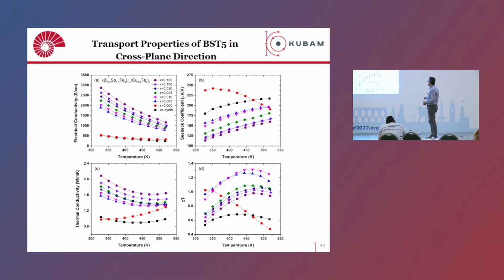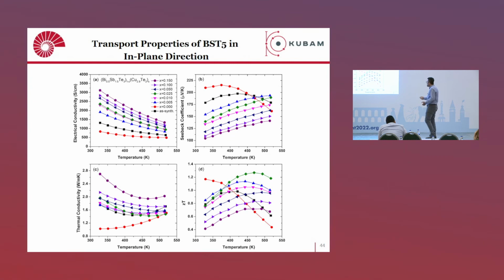So this was the cross-plane direction. We see a similar effect in the in-plane direction. The trends are almost the same: higher electrical conductivity, lower Seebeck, and a little bit higher thermal conductivity. The ZT is around 1.2 when 10-minute ball milling is applied, and at higher temperature, a copper telluride addition of, let's say, 0.025 gives much higher ZT values, which means that by introducing these nanoscale secondary phases, you can optimize the thermoelectric efficiency or performance of these materials.